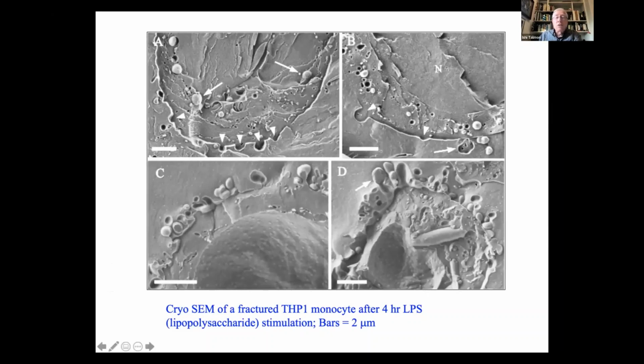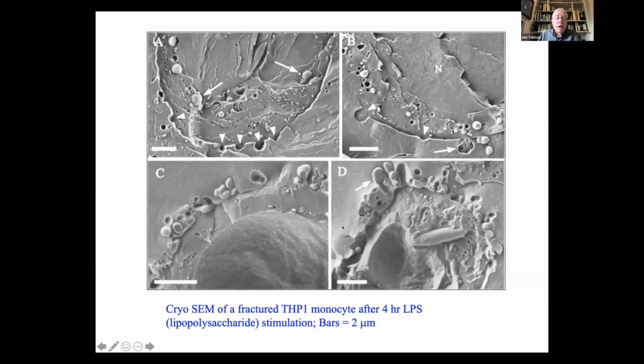This is probably the most important picture because I think this relates to slide 24 of Kelly's talk, and this is what Naama did. She was able to actually capture the process of the budding of the extracellular vesicles. So you see here some of the beginning of the buds. Here you have some completed buds, and some, in fact, EVs that are completely free. And again, just a last remark, here you can see very nicely the nucleus with the nuclear pore seen very, very nicely.